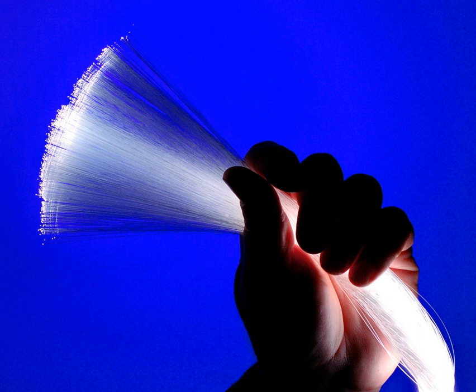When the reaction conditions are chosen to allow this reaction to occur in the gas phase throughout the tube volume, in contrast to earlier techniques where the reaction occurred only on the glass surface, this technique is called Modified Chemical Vapor Deposition. The oxide particles then agglomerate to form large particle chains, which subsequently deposit on the walls of the tube as soot. The deposition is due to the large difference in temperature between the gas core and the wall causing the gas to push the particles outwards. The torch is then traversed up and down the length of the tube to deposit the material evenly. After the torch has reached the end of the tube, it is then brought back to the beginning of the tube and the deposited particles are then melted to form a solid layer. This process is repeated until a sufficient amount of material has been deposited. For each layer the composition can be modified by varying the gas composition, resulting in precise control of the finished fiber's optical properties.